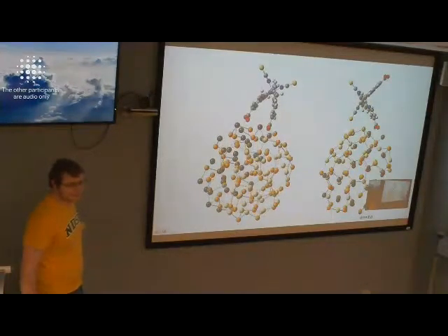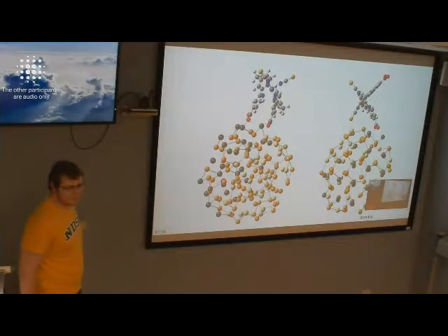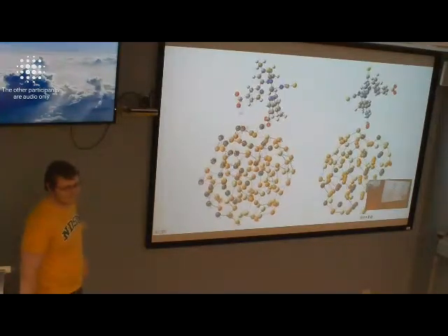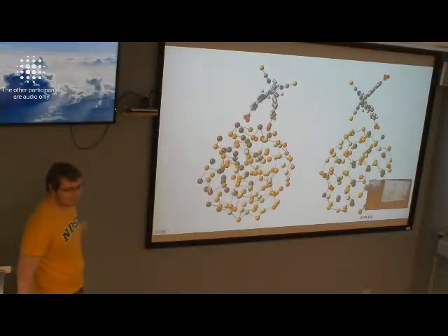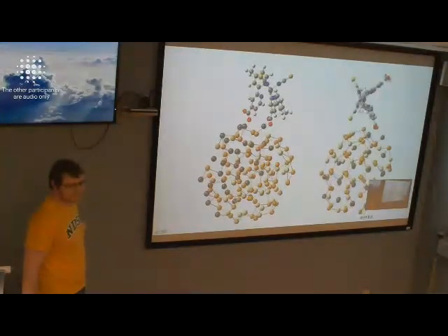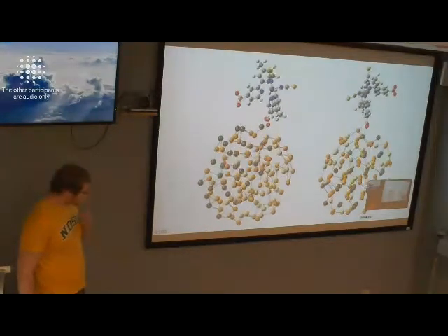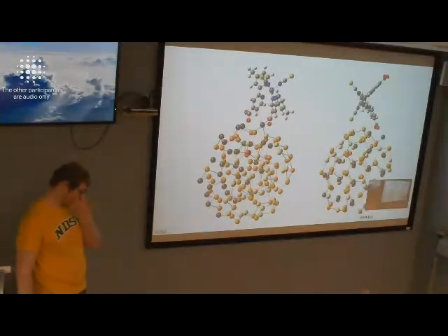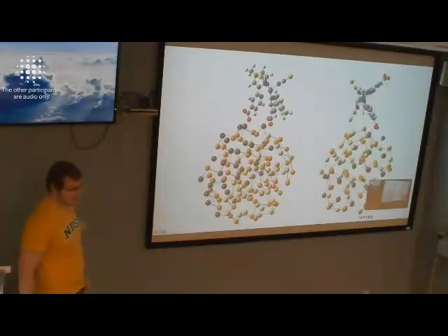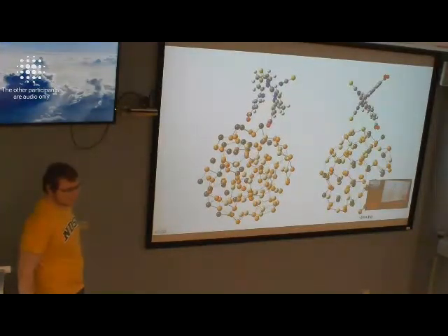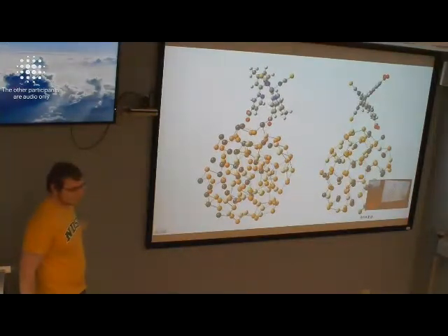This already splits your positive and negative charges, and more so when you have different materials, lead and cadmium, rather than a surface with just lead and selenium, or just cadmium and selenium, right? Yes. So at the interface, you expect a much bigger dipole moment than on this surface or that surface. Although the dipole of cadmium selenide is higher than the dipole of lead selenide.